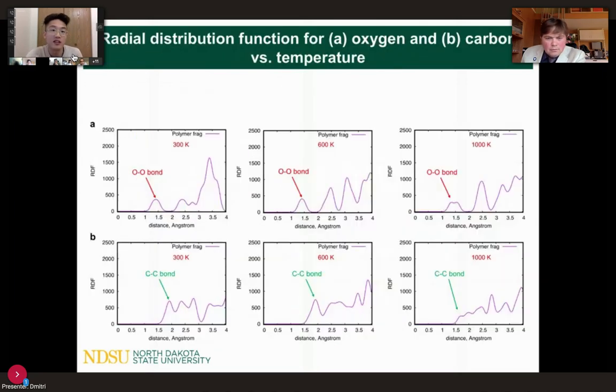We further investigated the radial distribution function for different types of atoms at a wide range of temperatures. The RDF here describes how the density varies as a function of distance from a reference particle. Actually, there's no big difference at lower temperature. However, if you look at the red figures on the right side, the peak becomes broader, both for oxygen to oxygen bonds and carbon to carbon bonds, which indicates the increasing degree of amorphization. Moreover, the intensity at a high temperature is pretty much lower than the intensity at a lower temperature.